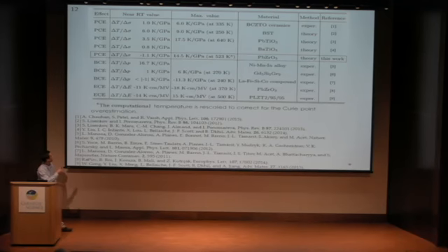We see our negative sign agrees with the electrocaloric effect that was found in the same material. If we look at the maximum value, something very interesting is that, especially compared to the electrocaloric effect in the same anti-ferroelectric material, we have a very large positive ratio, while in the electrocaloric effect they have a very large negative value. So this is also very nice for potential applications.